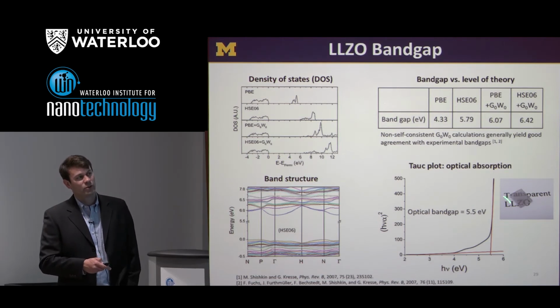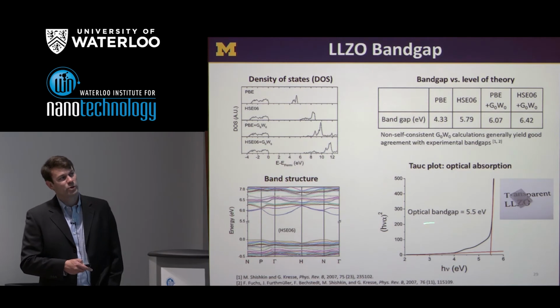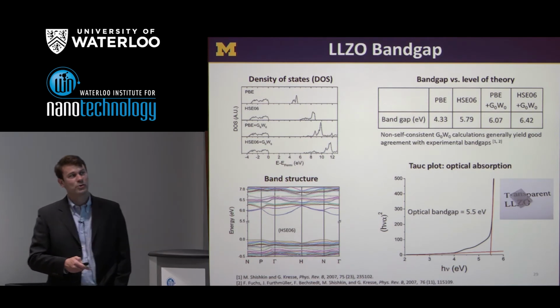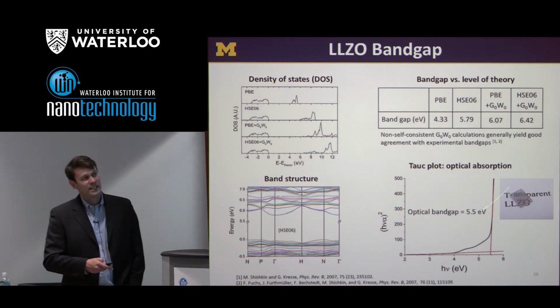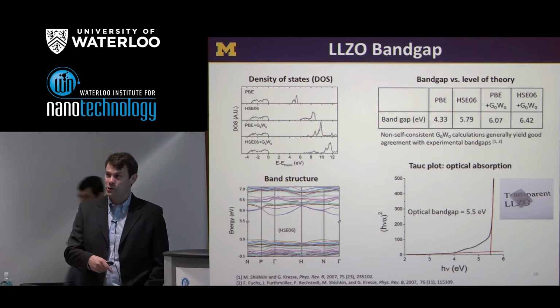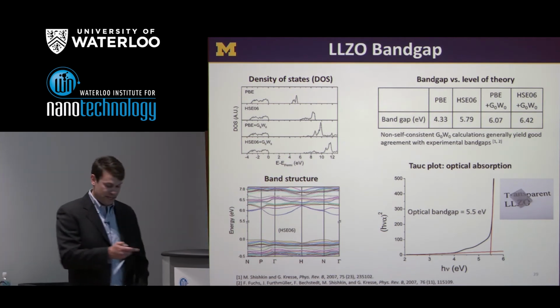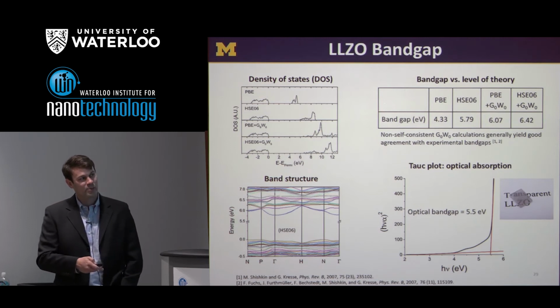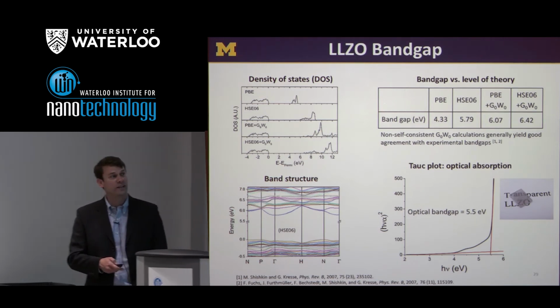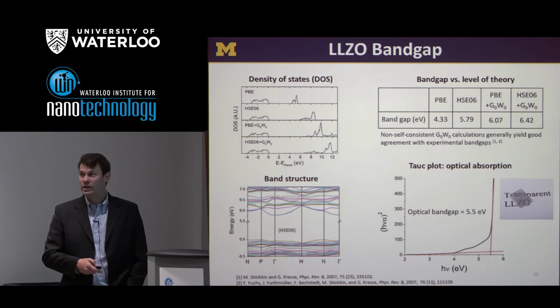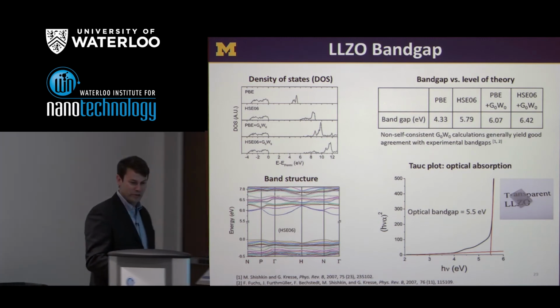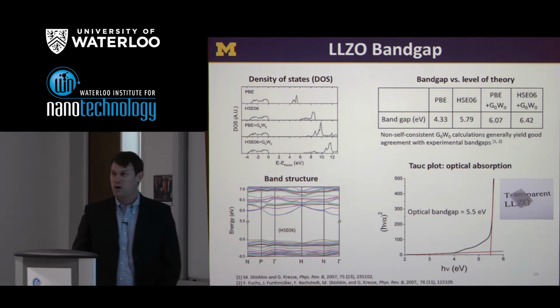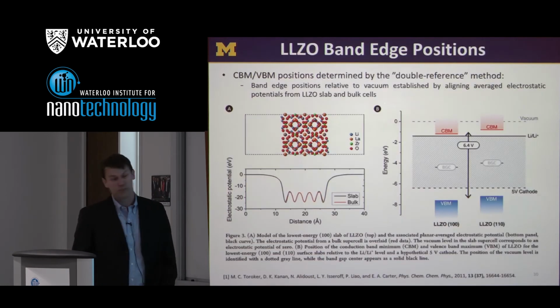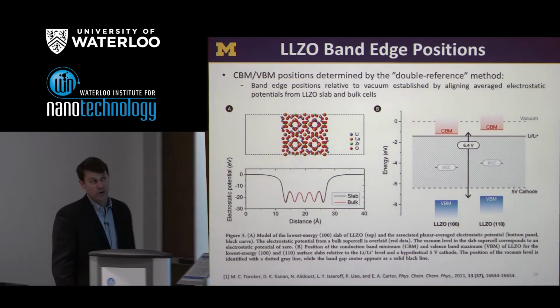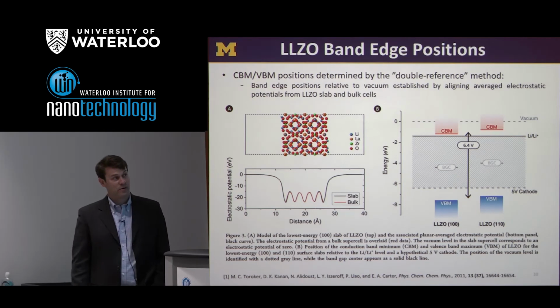And I'd say that agrees rather well with an absorption measurement done on a transparent sample of LLZO. Ideally, we'd like to compare the calculations to photoemission data. Absorption data can underestimate the band gap a little bit due to, for example, excitonic effects. But even with that, we're doing quite well. So it would seem LLZO has a nice wide band gap, which would enable, in principle, the use of LLZO in a battery that would have a high voltage.